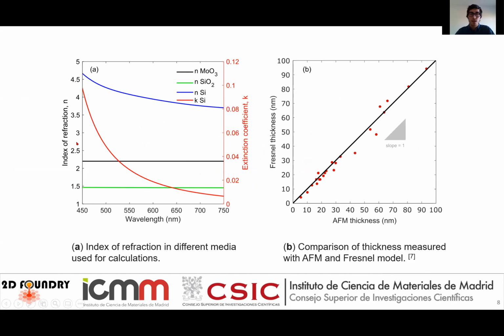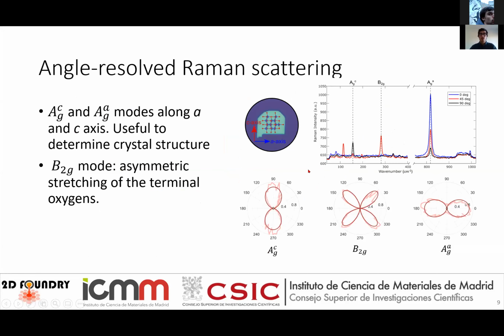These are the indices of refraction and the extinction coefficients that we have used in our calculations. And as you can see, this method to calculate the thickness is a reliable one, and apart from that it is fast, because the Fresnel thickness calculated with this model and the AFM thickness measurement of the same flakes form a slope of almost one. In fact, you do a regression model, and you get a slope of 1.02. So yeah, it fits very well, and pretty good. Apart from studying the thickness of the flakes, you can use this method to calculate the thickness and then use it for a later slide.